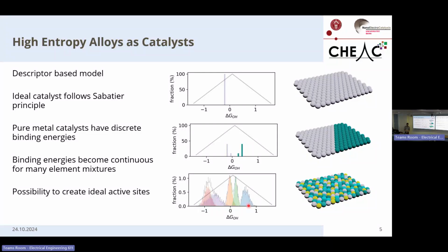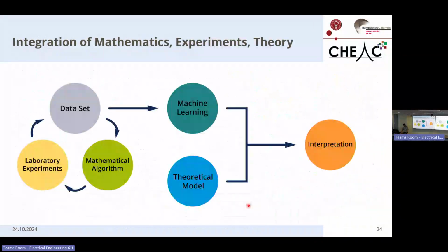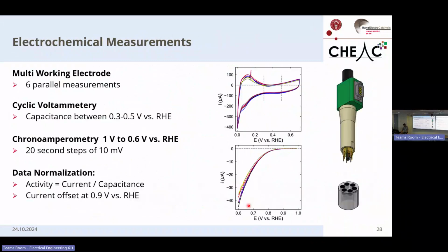For your system where you have 6 electrodes on the RDE, how do you know that there's not some dissolution occurring that is then changing the properties of the catalyst from one electrode to another? You mean crosstalk in this case? What I did is take the same catalyst in all of the 6 electrodes. It's the same material everywhere, so it doesn't matter whether it would be 1 electrode or 6 in parallel. They're not cross-contaminating each other. You're just doing 6 repeats. 6 repeats at the same time.